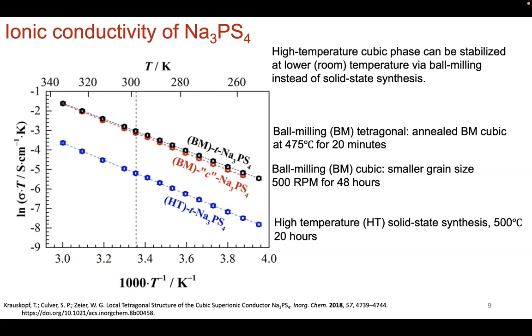The missing slide would have said that the local structure of this cubic phase looks like that of the tetragonal structure. If you look at the sodium ion and its nearest neighbor, sulfur, the local structure for the cubic and the tetragonal looks very similar, whereas the average structure is quite different. We can do X-ray diffraction and Rietveld refinement and look at the average structure and say, well, one is clearly cubic and the other is tetragonal. But the local structure, when you sit on one sodium ion and look at the nearest neighbor configuration, is quite similar. The ball mill cubic and the ball mill tetragonal look like each other, and thus the resulting ion conductivity that you can measure is the same. So that was the punchline.